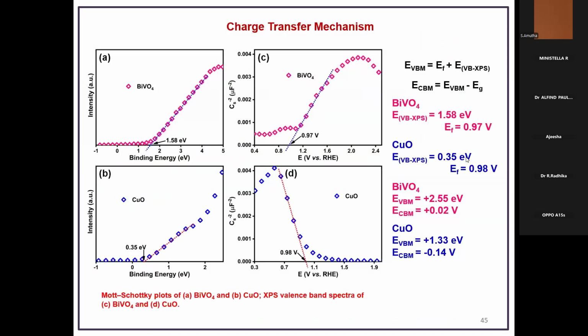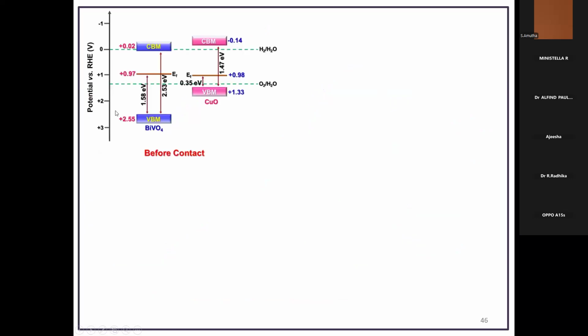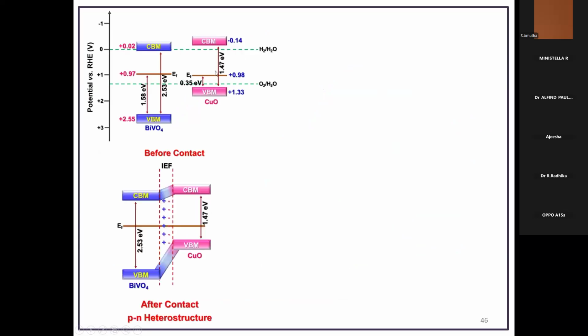Then we want to predict the charge transfer mechanism. For that, we have done the XPS and UPS analysis to know the valence band maximum position. We have calculated the valence band maximum position, and we have measured the Fermi level by using the Mott-Schottky analysis. Then we have adapted the values in the following formulas. Finally we arrived at this energy level position for both semiconductors. This is before contact, this is after making contact.